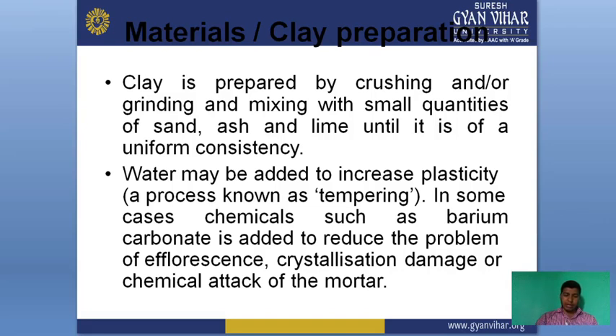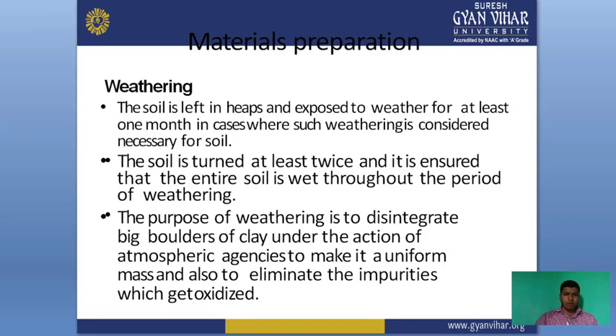The clay is left for at least one month where weathering is considered necessary. The soil is turned at least twice and it is ensured that the entire soil is wet throughout the period of weathering. The purpose of weathering is to disintegrate big boulders of clay under the action of atmospheric agencies to make it a uniform mass and also to eliminate impurities which get oxidized.